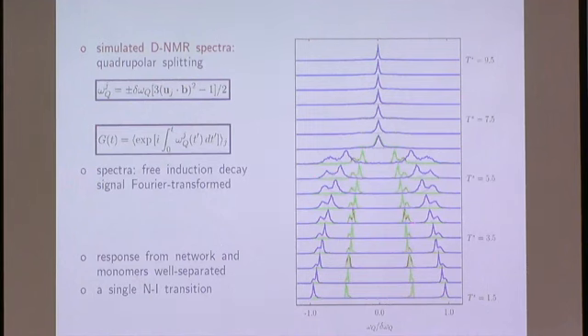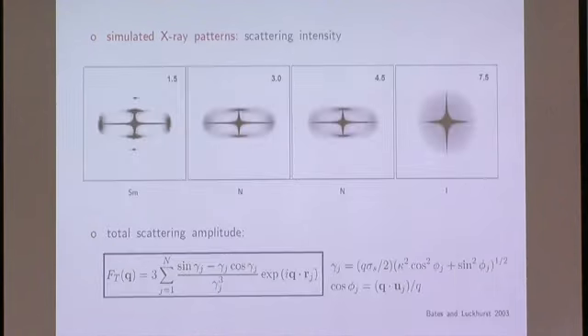Then the other two sets of curves, red and green, correspond to an NMR field directed perpendicular to the directors, along X or along Y, and their overlap actually suggests that the system is quite uniaxial. Okay, so the other experimental observable we decided to look at were the simulated X-ray patterns.